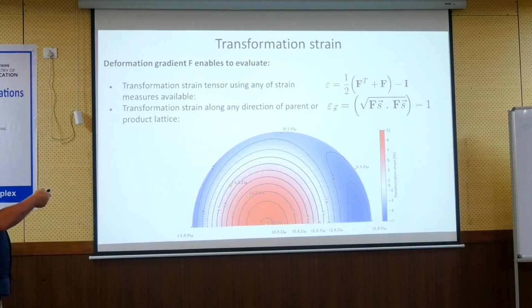this is actually the product of the gradient of F, the transformation gradient, deformation gradient, and with this you can get the, okay, we are interested in the maximum elongation along some particular direction, which is this epsilon. You can obtain this epsilon, and you can have it along either austenite or martensite phase. And here it is plotted with respect to martensite phase. Normally in the literature you will find it always with respect to the austenite phase.